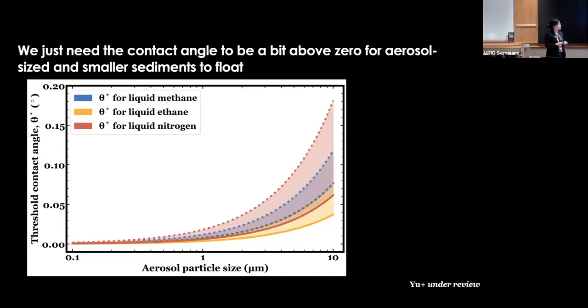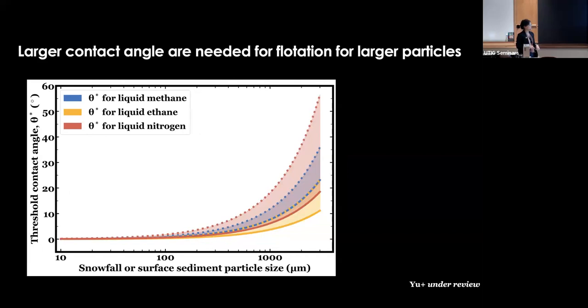Okay. And what we found is if you have very small particles, like aerosol sized particles, between 0.1 and 10 microns shown on the x-axis, you only need just a little bit above 0 contact angle to make the capillary force big enough to counteract gravity, which makes sense because the particles are so small, right? But if you hit much bigger particles, like small snowfall size or surface sediment size, you actually need much larger contact angle to make things float. Okay. And now with our surface property data from the database, we can estimate the contact angle that's formed between all the different ices and the liquids on Titan.